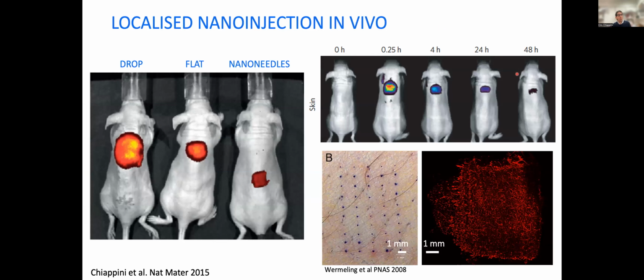But you're not really limited to what you can do in vitro. I think that what is more interesting is the ability to nano-inject topically to specific locations in vivo and deliver genes that way. You can clearly see that when you use nanoneedles, you can very well define the region in which you want to deliver, differently from whether you just drop your payload onto the animal or whether you are using a flat chip that does not have needles. And more importantly, if you deliver with these 2 approaches, your payload gets washed away immediately at time 0. But if you deliver with nanoneedles, you can retain the payload at the site of delivery for up to 48 hours and actually even longer.